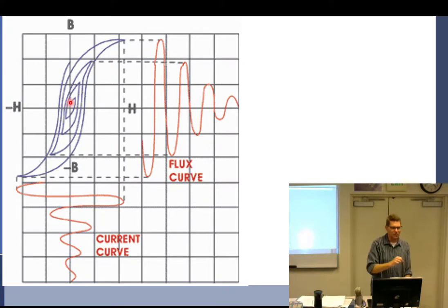When I hit the demag switch, a mechanism would move this arm all by itself all the way around the face of the clock. So 2, then 3, then 4, then 5. It would hit every single one of them and give it a half shot of magnetism till it got all the way down to the highest number, which was the lowest setting. Don't ask me why. And that would demagnetize it.